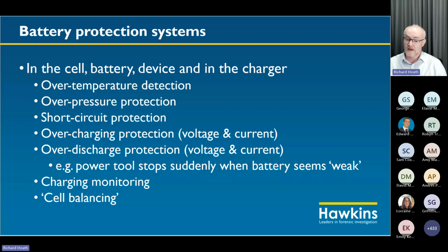And the protection systems monitor the temperature of the cell to prevent overtemperature. There are some that look at the pressure in the individual cell. So if the pressure starts to increase, if the battery begins to fail, there's an automatic venting process. Short circuit protection is monitored by battery management units also, in order to keep the charging process and the discharging process within those bounds of voltage, current, and temperature. And as well as that, where you have lots of individual cells connected together to form the battery, you monitor the charging process to ensure the cells remain balanced so that all the cells get an equal amount of charging. And if a cell starts to become weak and gets overcharged, that can be noticed and acted upon before anything goes wrong.